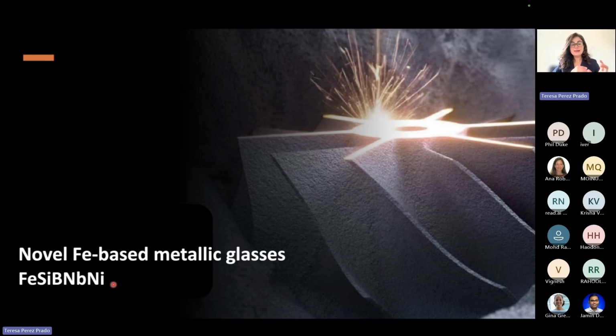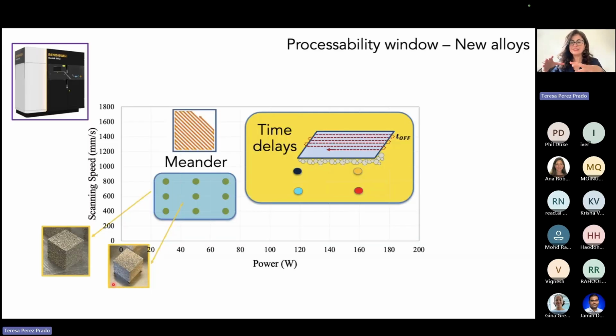But by adding nickel, they were able to increase the glass formability from about 100, 120 microns to about 1 millimeter. And then we thought, okay, let us now use these newly developed alloys, apply what we learned about process optimization, and let us see if we can really reach the target. So this is what we did, and I'm going to show you what happened. And this is where the good news are coming. I promise you some good news in the end.